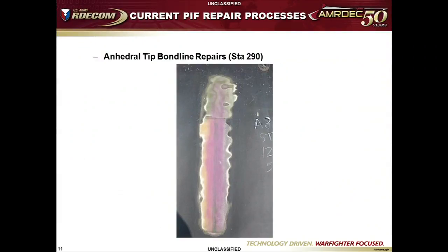The other one, and this one was a huge concern to pilots, where the anhedral tip is attached to the Mike model main rotor blade. It's bolted on and bonded on. Where that bond line is, there's a seam that's filled with an adhesive filler. The adhesive filler that was used at the factory, which I believe is EA 9395, has about a 2% elongation to failure. If you go up and you fly this aircraft for several hours, eventually, out there at that extreme tip, that adhesive starts to fracture.